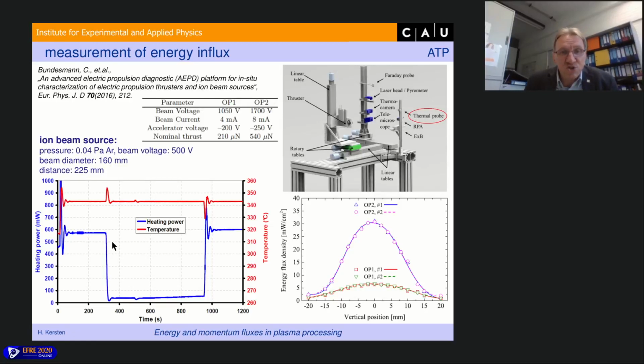And that means this jump in the heating power of the sensor is the power which is coming from the source, from the plasma or from the ion beam source. So you can directly measure by this jump. Here in this case is an influx of about 500 or 550 milliwatt. And this was, for instance, tested in a setup for electric propulsion tests.